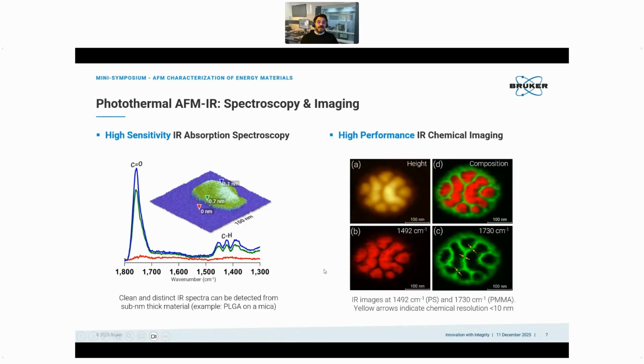Now that's one thing. The other thing is when we come to see things and add into it the understanding of what we are seeing. So this example is a topography image of a copolymer nanostructure. So you can estimate the size by looking at the scale bar, right? So this is the topography. Now, instead of doing spectroscopy by sweeping the wave number of the laser at one fixed point, we will send the laser pulse at one specific wave number all the time, and then we will scan the surface. So what happens is, we will only measure a bending or amplitude of the cantilever at areas of that surface where that wave number is absorbed.